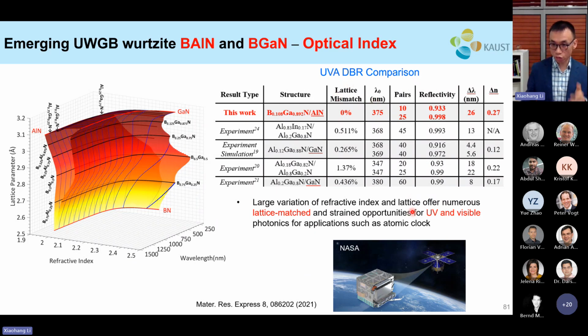For instance, the UV VCSEL has been very important. Actually, in the US, there have been multiple projects from DARPA for UV lasers and VCSELs, because it is very important for the future development of atomic clocks. However, if you use the AlGaN/GaN system, you always end up with some lattice mismatch, and the delta n is also not as large.